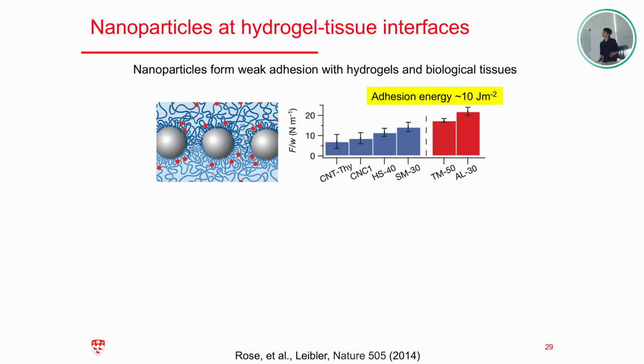And the last advantage of ultrasound I want to show you here is nanoparticle adhesion. Nanoparticles have received a lot of attention, right? They have enabled amazing applications in a variety of areas. However, when it comes to the hydrogel-tissue interface, nanoparticles have been known to enable only weak adhesion. So why is that? Here is a paper published in Nature in 2014 that proposed the use of nanoparticles to form adhesion. The physical picture is the following. When you place the nanoparticles at the interface, they adsorb the polymer from both sides and enable the adhesion, mainly based on van der Waals force or physical interaction between the polymer and nanoparticle. But at the end of the day, you only get a very weak adhesion energy.